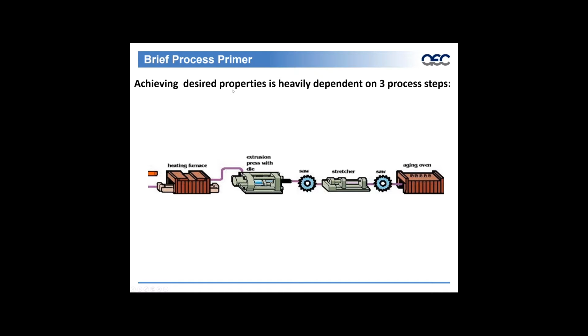Achieving desired properties is heavily dependent on three processes that exist within the extrusion operation. And here we represent the general stream of an extrusion process. We have an oven, we have an extrusion press with a quench box right after the press, a cut down saw, the stretching application, another saw that cuts down to lineals, in our age oven.